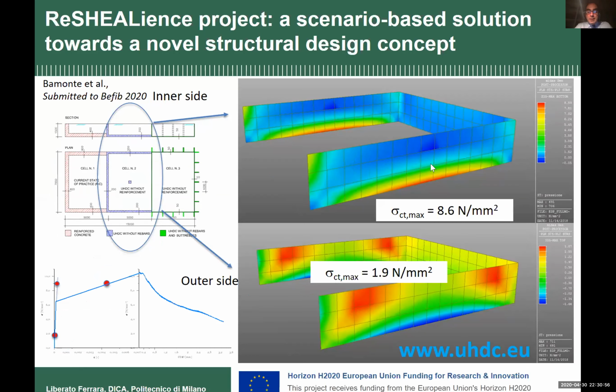Well, the level of stress is higher. On the other side, it's lower than 2 Newton per square millimeter. Here on the bottom, you can see that it's a little bit less than 9 megapascals.